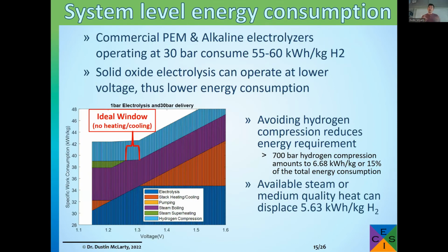So we put all this together. We put the heat recovery system together, the steam generation, the electrolysis itself, the hydrogen compression, and we get an overall system energy consumption. And so this stack chart is really showing you, as a function of voltage, what are the contributions to the overall energy balance. The vast majority is the energy going into the electrochemistry of the water splitting, so following this linear slope here with voltage.